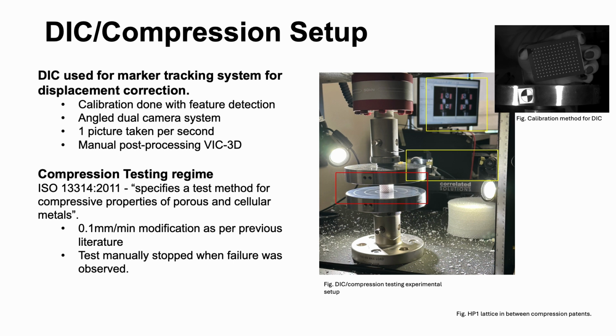We calibrated the system using the grid, and if you take a look at the grid here on the top right, we see that the grid has white dots, some with holes, and the dual camera system can detect these features, and it actually takes a picture when the feature is detected. So once a certain amount of images was taken, we received a score, and if it was less than 0.1, then it was sufficient. For the compression test, we set the crosshead speed to 0.1 millimeters per minute as specified for ISO standard. When the lattices failed, then the test was manually stopped.